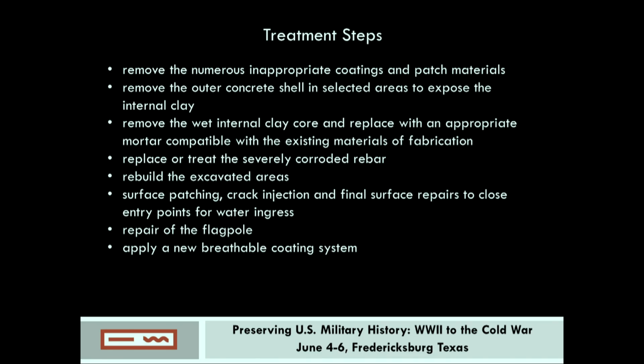You can see most of the steps on this slide, so it was a multi-step treatment, including taking off the coatings first, removing the concrete shell, removing the wet internal clay, replacing or mitigating the severely corroded rebar, rebuilding those excavated areas, patching the surface, crack injection to prevent water getting in there anymore, repairing of the flagpole, which was also a big problem, and application, very importantly, of a new breathable coating system. We also tested the concrete for presence of asbestos and lead because we were worried about that, and that proved negative.